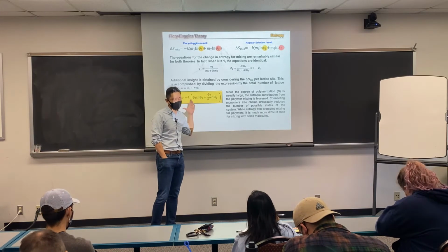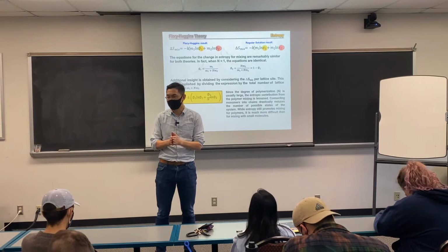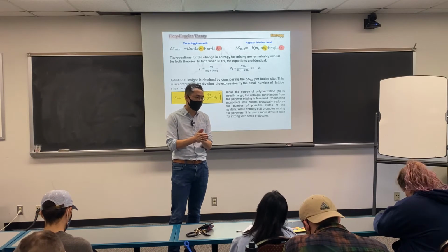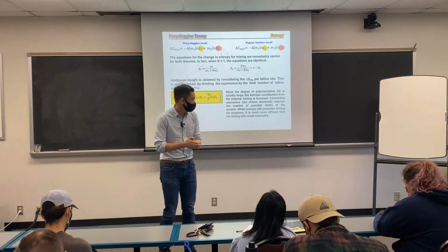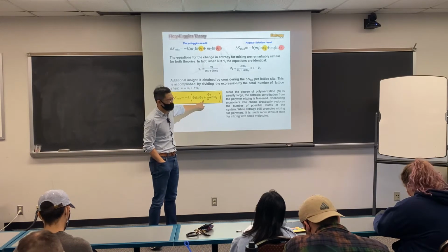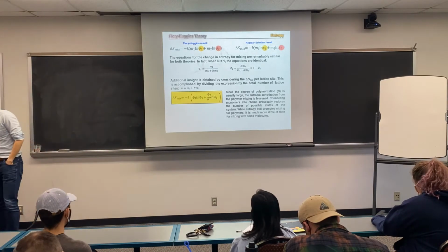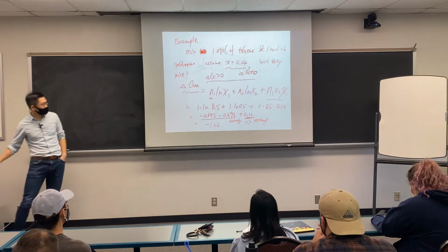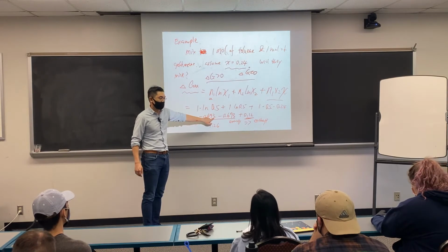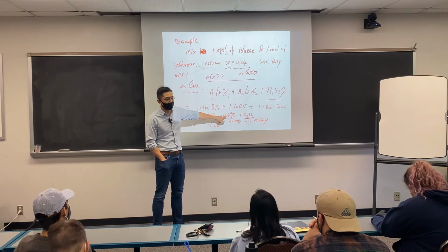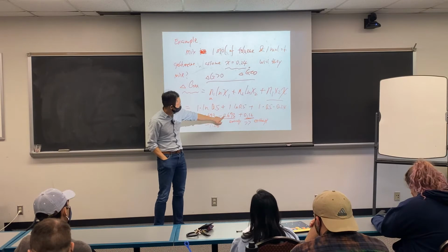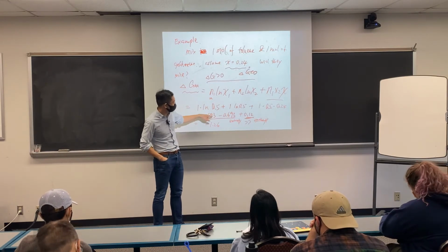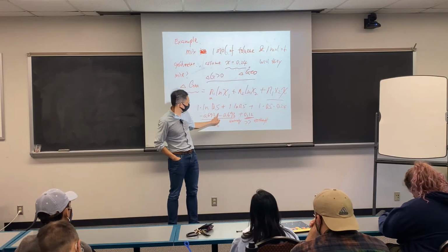If you see this, you will see entropy always favors mixing. When we replace a solvent with a polymer, what we did to the system is we lower the entropy contribution from the polymer. As we did in the last calculation, we know this is roughly minus 0.693. That's the contribution of toluene, that's the contribution of hexane. If we replace it with a polymer, with degree of polymerization, let's say 100, this term is going to be 0.00693. You don't have much contribution anymore from the polymer. So when you combine together, your entropy will be lower, although it's still going to be higher than the entropy in this case, even if we cross away this part.